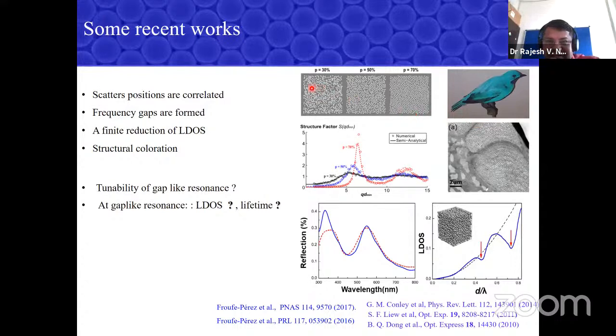And people try to simulate this using Monte Carlo simulations in the computer. You can see that you have 30% disorder, then 50% disorder increasing, and there's 70%. And then you look at the structure factor. Structure factor is a factor which will tell you there is a resonance in scattering. Probably you must have done it in solid state physics. The structure factor shows a peak, and this has been theoretically shown to even affect the density of photon states. So we were quite excited by these systems, and we thought about how to make this disordered sample, when I say a controlled disordered sample or a correlated disordered sample.